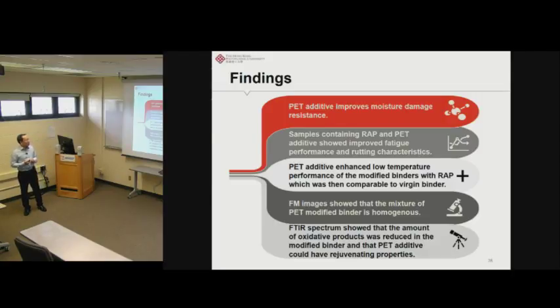We also found that the PET additive will not change the low temperature grade of the binder. It even has a slightly positive effect. The FM image shows that the mixture of the PET modified binder is relatively homogeneous, and our FTIR spectrum test results indicate that the PET additive has a certain rejuvenating effect on the binders.